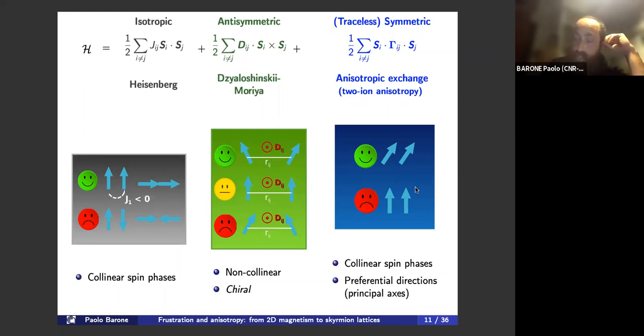Instead, the anisotropic exchange displays a behavior which is much more similar to the dipole-dipole interaction. So it tends to form collinear spin phases aligned along preferential directions, which are nothing else than the principal axes of the tensor. Now, from here, we immediately see that we have two kinds of competition. There is an energy competition between the Heisenberg and Dzyaloshinskii-Moriya interactions, which would promote some noncollinear phase. And we also have a competition between the preferential directions selected by the anisotropic exchange and the Dzyaloshinskii-Moriya vector, because this interaction also tries to select an oriented plane where the spins want to rotate.